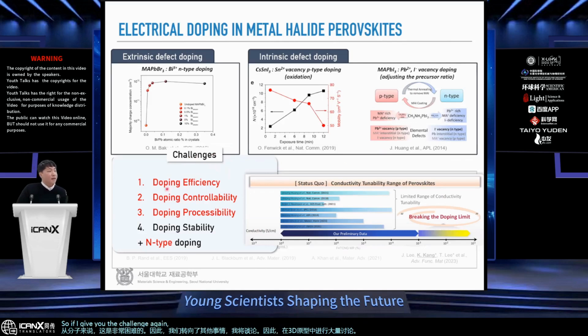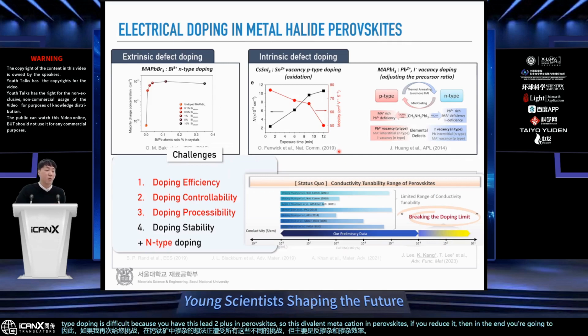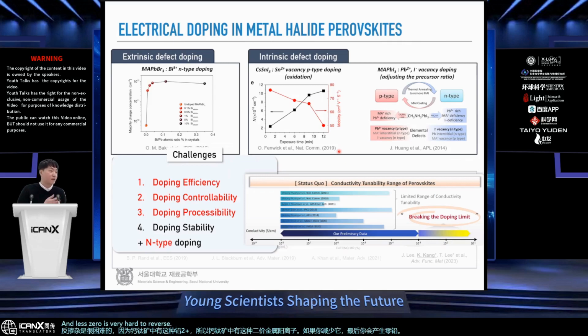So if I give you the challenges again, the idea of doping perovskites is suffering from all these different challenges, but mostly the n-type doping and the doping efficiency. N-type doping is difficult because you have this lead 2 plus in perovskites. This divalent metal cation, if you reduce it, then in the end, you're going to create lead 0. And lead 0 is very hard to reversibly, let's say, oxidize. So once you reduce to lead 0, then they may not be coming back. So n-type doping is quite difficult.